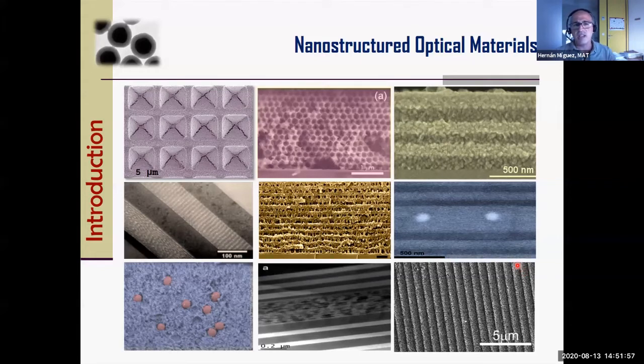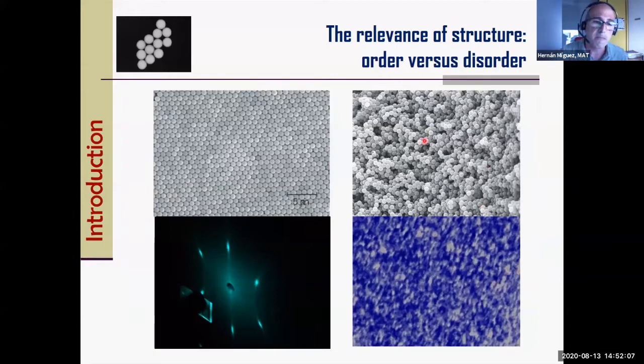So let me just show you briefly what I mean when I say that the optical properties depend on the structure. Let me just give you a couple of examples that I think are very illustrative. So what you're looking at here are two different materials based on the same building blocks. This little picture here is a transmission electron microscopy image of latex or polystyrene spheres. In this case, we have arranged them in a perfect face-centered cubic lattice. So basically, this is like a crystal, but instead of having atoms in the crystalline positions, we have large spheres that are a few hundreds of nanometers in size. And with the same spheres, we can make a completely disordered material.